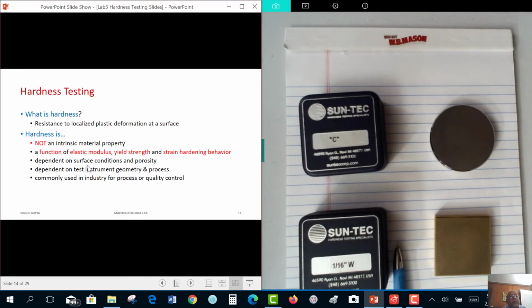But it is also very dependent on surface conditions and porosity. So whether the surface is rough or smooth, it can change the hardness. Whether the surface is less or more porous, it can change the hardness. It's also dependent on test instrument geometry and how we measure it. The key thing is it's commonly used in industry for process or quality control. As you have seen, it is a very quick, very inexpensive process. So often when a material is undergoing a thermal or mechanical process, we pass samples along so that we can monitor their hardness and see whether they have gone through the right process or not.